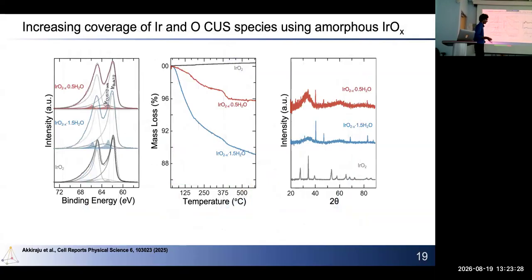That's when we said, can we design new iridium oxides which have a higher content of these oxygen CUS species? With the idea being that if we have more of these species, we could lower the temperature for methane activation.